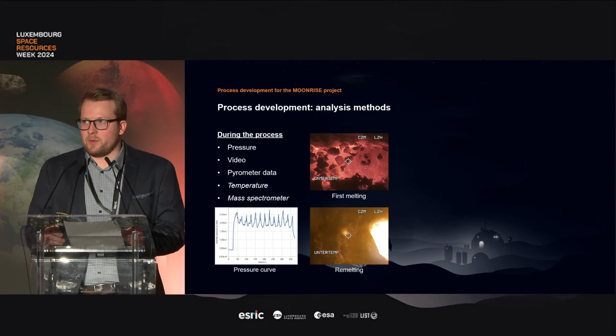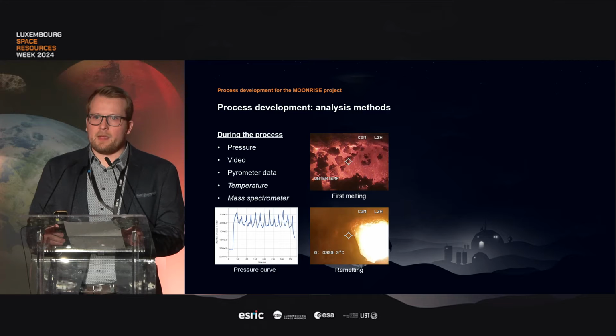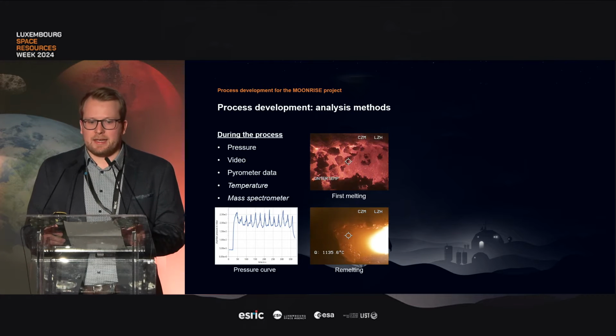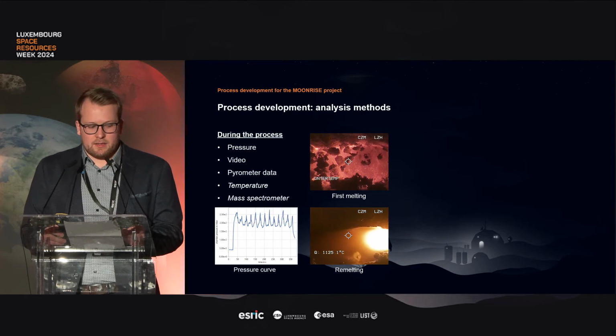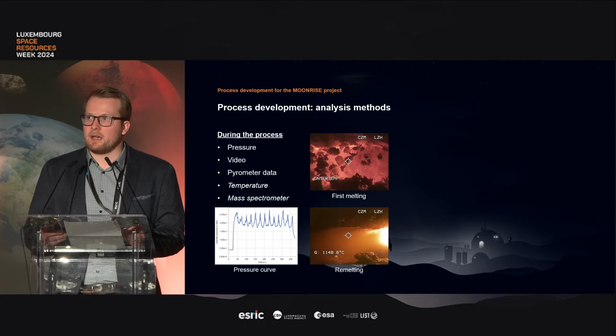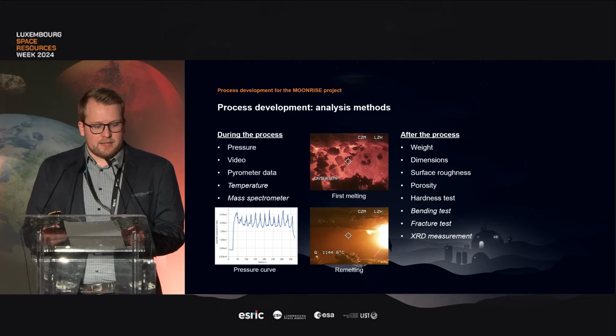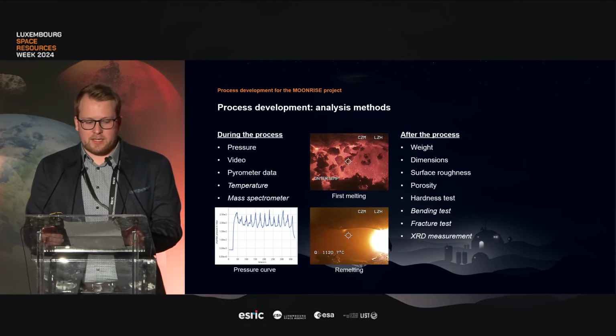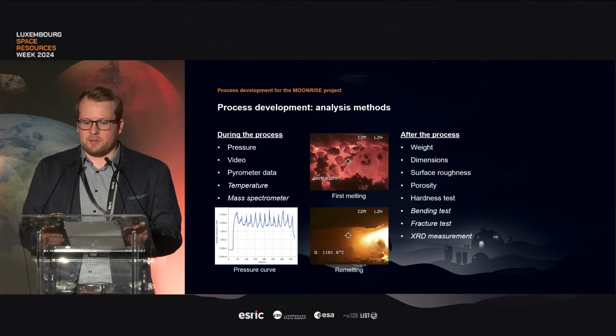Then in the future, we will also be able to measure the temperature of the sample and of the powder bed, and we will add a mass spectrometer to the setup to figure out the elements that are in the gases that are evaporating. After the process, we take the samples out of the vacuum chamber, we weigh them, we measure the dimensions, and we analyze the surface roughness.